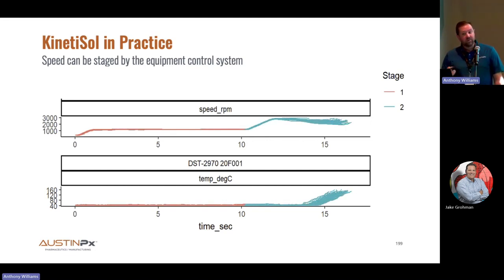But we had a process where we had observed some segregation, and we needed to deliver a bunch of clinical trial material. And so what we did is we roller compacted the material before we fed it to the machine just to take away that segregation. There's more than one way to do that. We could have gotten different particle size distributions of the materials and not had to roller compact it. But we needed to deliver clinical material. We had the machine. We did that.